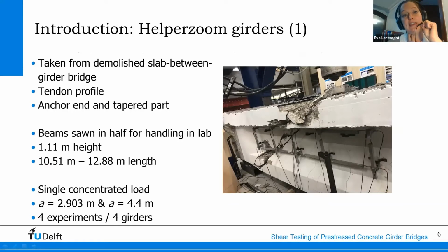These specimens are taken from a demolished slab between girder bridge, the Helperzoom bridge. This bridge had to be demolished because of the redesign of the perimeter around the city of Groningen. And since these are actual bridge girders, they have all the details that real girders have, and that not all typical laboratory specimens have, such as the parabolic tendon profile, with some of the tendons even anchored in the top flange. All the way at the end here, we have the anchor part, and then we have a part where the width of the cross-section tapers towards this part here where we start to have the thin web.